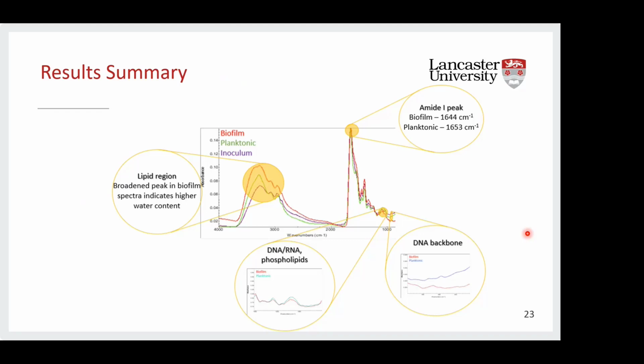I'd like to draw your attention to 4 of our key findings. Firstly, if we look at the higher end of the spectrum, we have the lipid region. This reveals water content, which is obviously much broader for the biofilms. The biofilm is this top peak here, and then you step down to the planktonic sample. Now, I did mention that we're using partially dry samples, but the biofilm still has an intact extracellular matrix. So this is going to contribute moisture that the planktonic cells don't have.